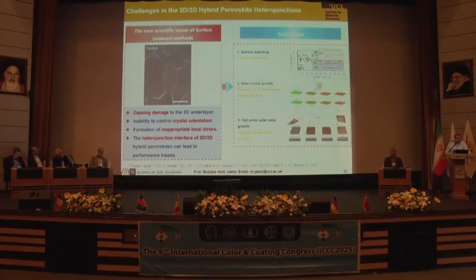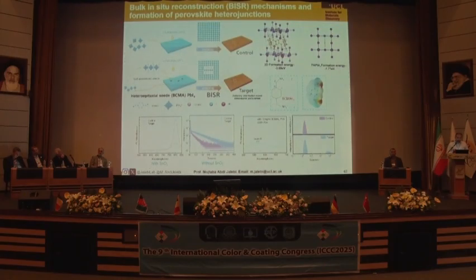One challenge is solvent matching, the other one is seed crystal growth, where you have seeds on top of your 3D and then have 2D on top. And the other approach is hot press. In all of these, it's very difficult to preserve the good crystal structure of the perovskite. So what we developed in this work, published last year in Advanced Functional Materials, is we put the seeds in the precursor solution of the perovskite, where you basically form the 3D across the 2D in one go. So you don't need to form your 3D first and then 2D, but you simultaneously form both 2D and 3D. And this helped us make a very robust thin film.